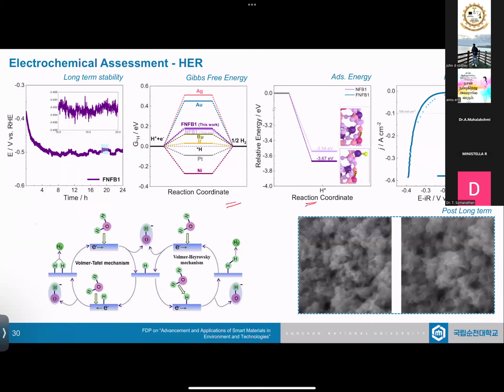We can see that just by bringing in a fluorine atom, the amount of adsorption energy has changed. The nickel is not getting involved in the reaction, whereas iron is directly getting involved in the reaction. And the Gibbs free energy is around 0.3 or something. Sorry, 0.2 or something. I'm sorry, I don't have the exact value here.